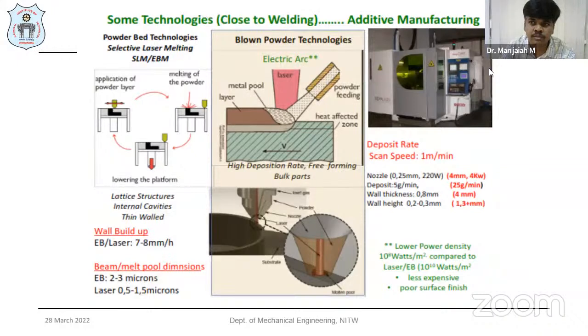If you see here, either the powder fusion process, direct energy deposition process, or WAAM process, the melting and solidification is very similar to a welding process. And what kind of grains are we going to get? As in TIG welding, the rate of solidification is very fast. Similarly, in the DED process or the additive manufacturing process, the rate of solidification is very fast. In a similar fashion, we are going to have columnar dendritic structures in additive manufacturing, whether in the powder blown technology or in the powder bed technology.